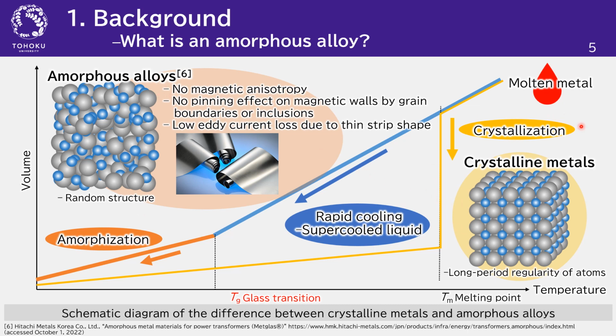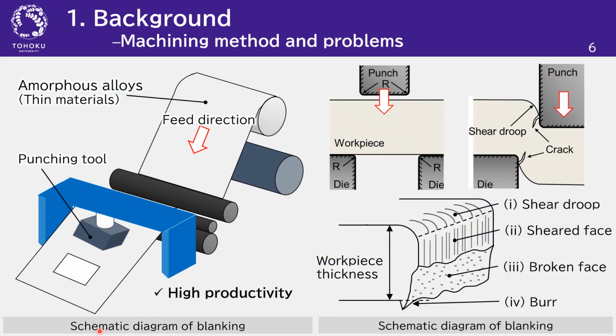Unlike ordinary crystalline metals, amorphous alloys have a random structure. Therefore, there is no magnetic anisotropy and no pinning effect caused by grain boundaries, and the eddy current loss is also low because the material is very thin. For machining such thin materials, blanking is often used. In blanking, a pair of punch and die is used to cut the material, and the material is broken by the propagation of cracks generated by the compressive force from the tools.